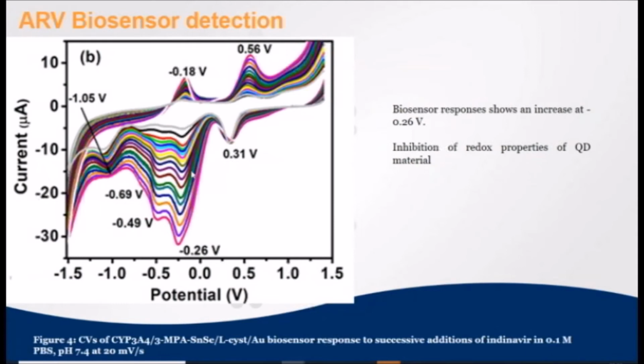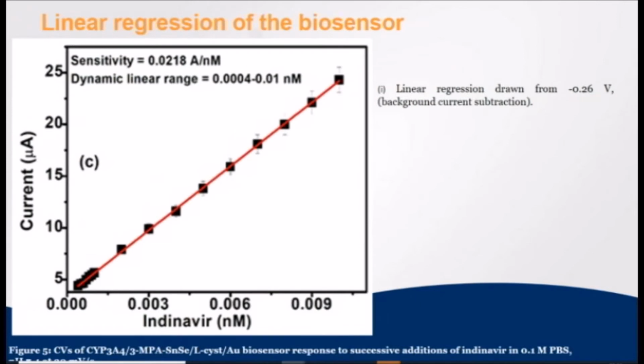The most important thing in this case is that we need to subtract the background from the sample. So before we go to our linear regression, we need to subtract the first addition from the background, the second addition from the background, so that we understand our linear progression and get a proper linear regression. After the subtractions, we plotted our linear curve. When you are developing these biosensor systems, you need to do the experiments 3 times so that you can get a proper linear regression, and also include the error bars.